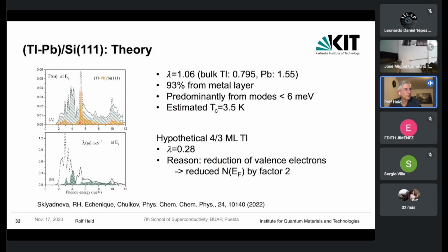And when doing the calculation for this system, we find indeed an even larger coupling lambda, which is somewhere in between the bulk value for thallium and for lead. A large contribution for the coupling comes from the metallic layer. The substrate is only contributing a little bit in this case. And we find again a very strong coupling to low frequency modes. And based on this calculated alpha squared F, we estimate a Tc of 3.5, which is somewhat larger than the experimental one.